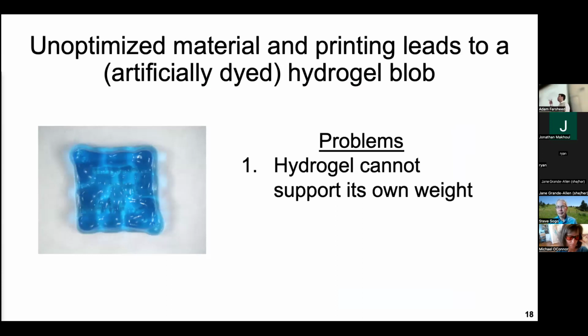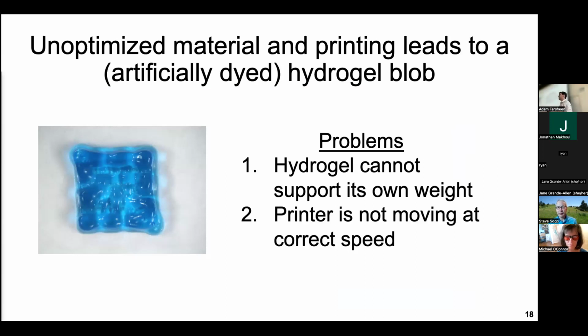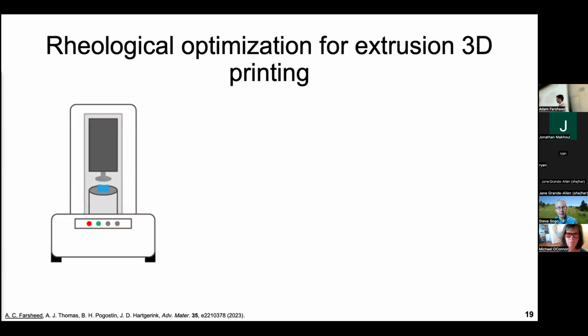And I want to point out two problems that we saw in this initial work. The first is that the hydrogel was unable to support its own weight. And so that's a problem with the material itself. As it tried to go upward, it just sagged and kind of sank. The second problem that we ran into is that the printer actually wasn't optimized to print at the correct print speed. And I'll dig into each of these two problems, both the material and the printing optimization, individually.